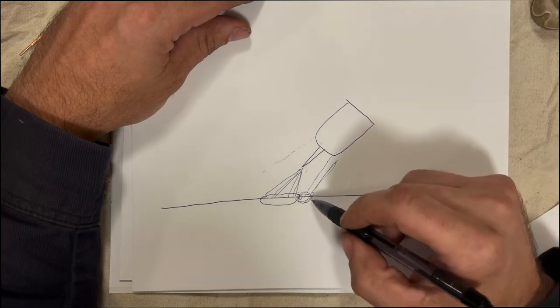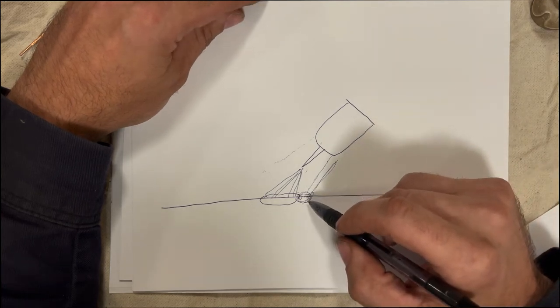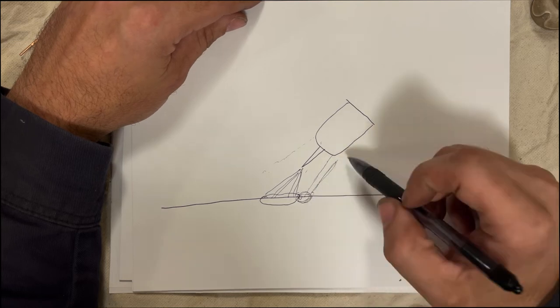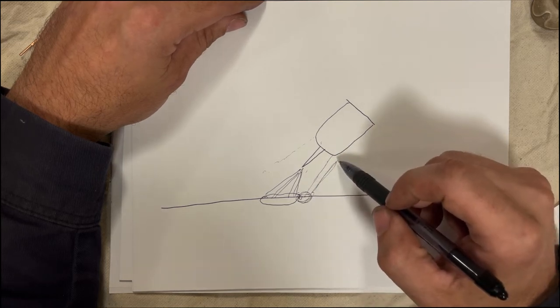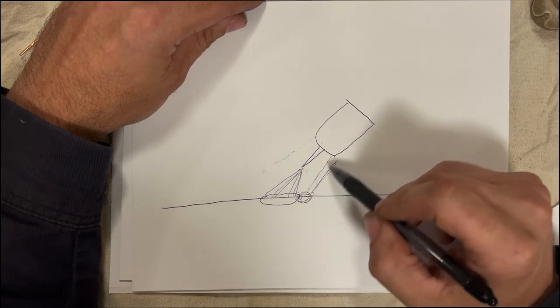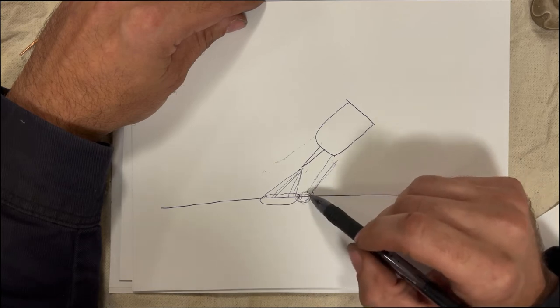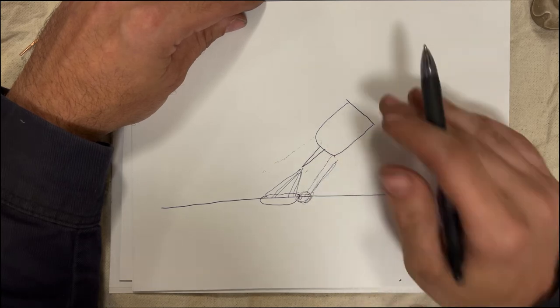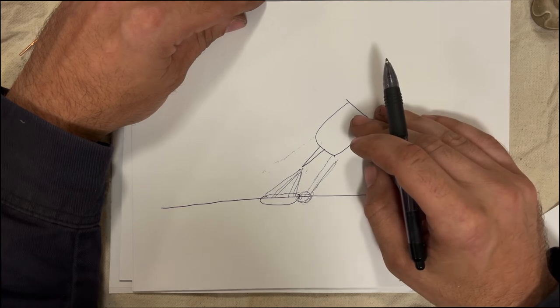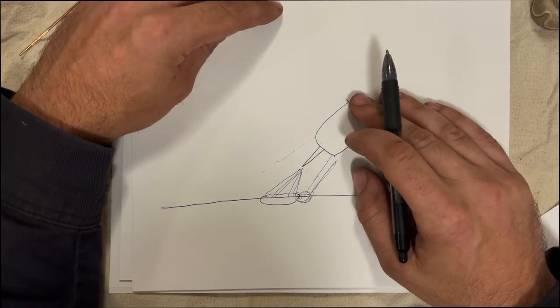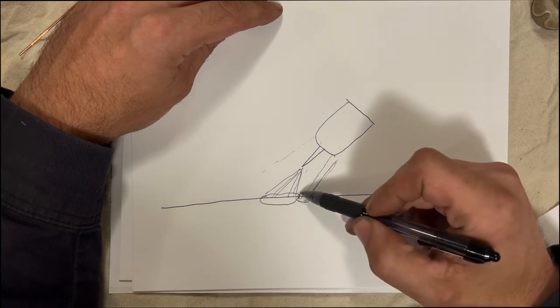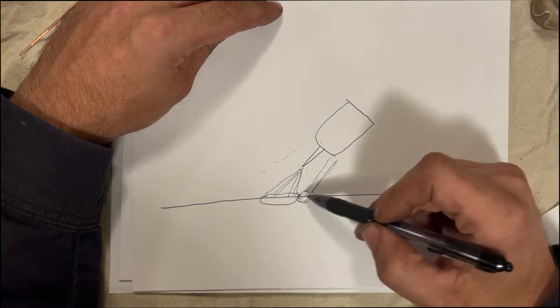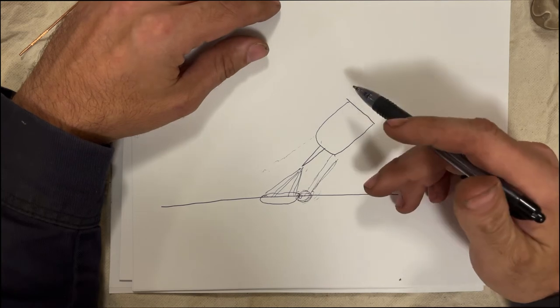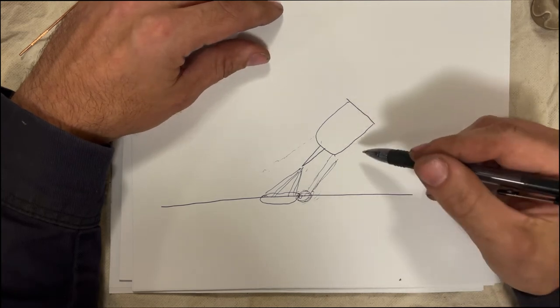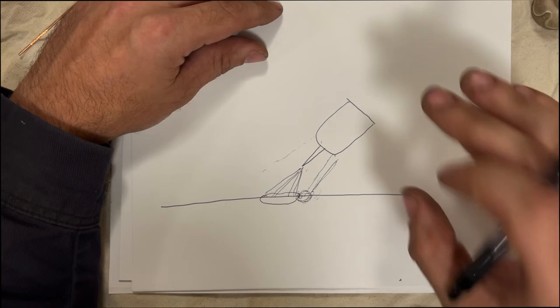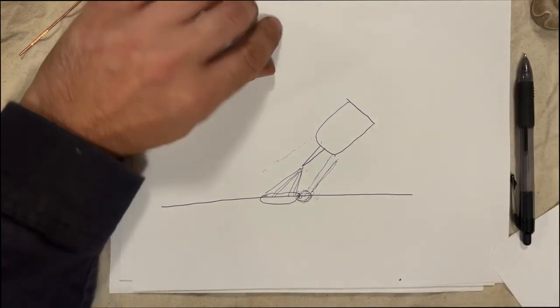So with stainless steel, rather than getting nice, say, yellow or silver welds, you're going to start getting dark gray or burnt looking welds. And that's because your argon shielding area here is not adequate. So if you're welding on something that has an issue with oxides like stainless steel, you got to run a bigger cup in order to get more shielding, and it basically gives the weld more time to cool down, so that when it loses that shielding, it's cool enough to where it doesn't severely oxide.